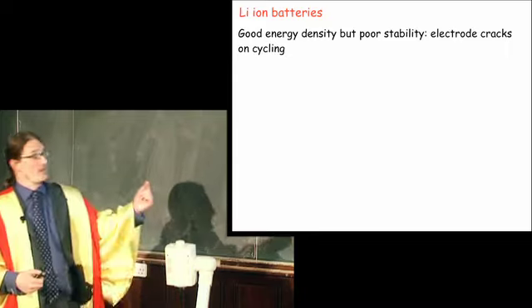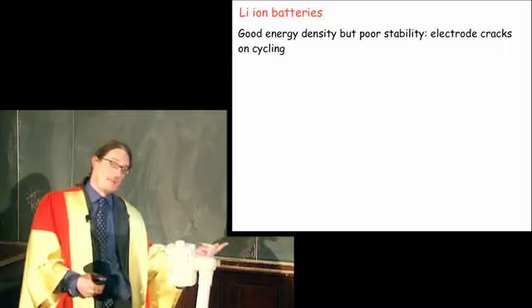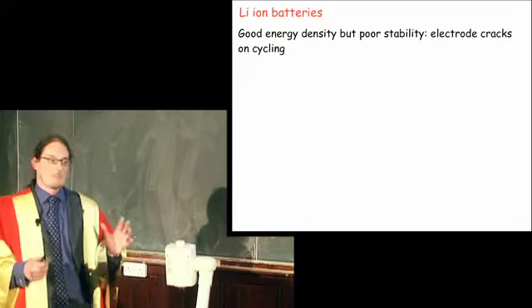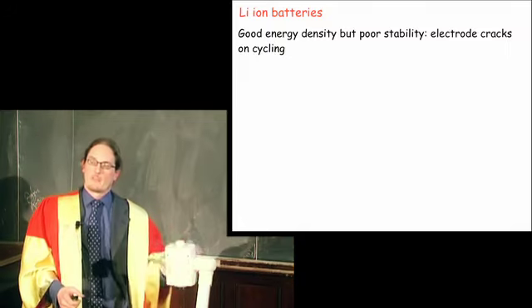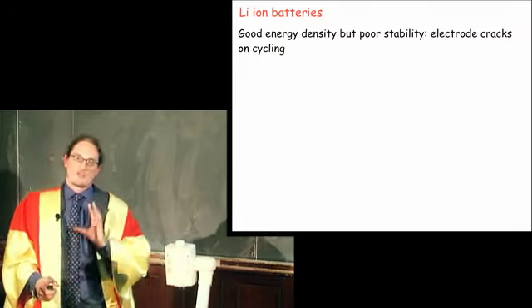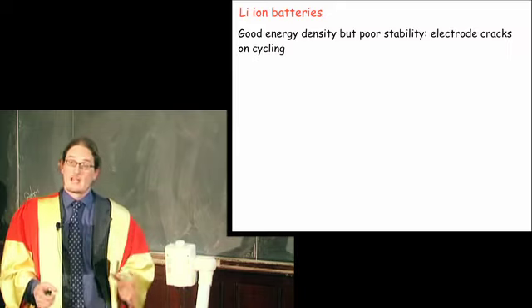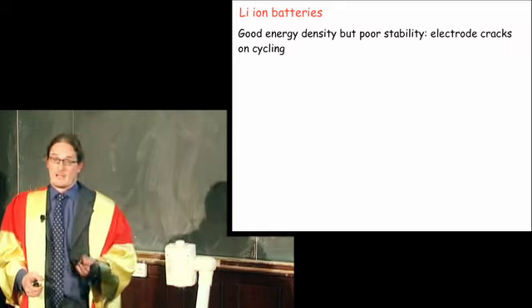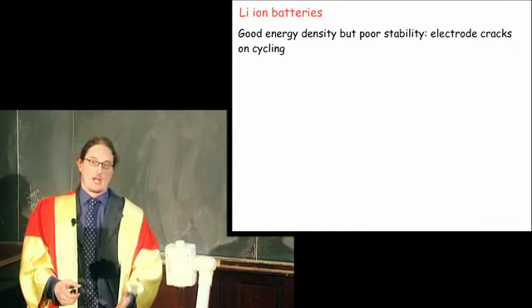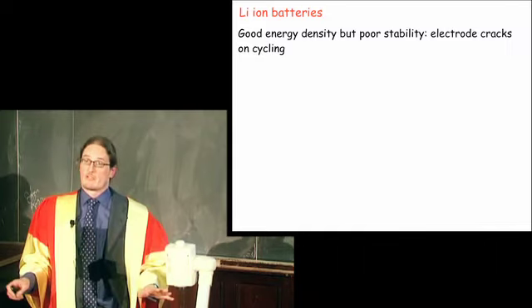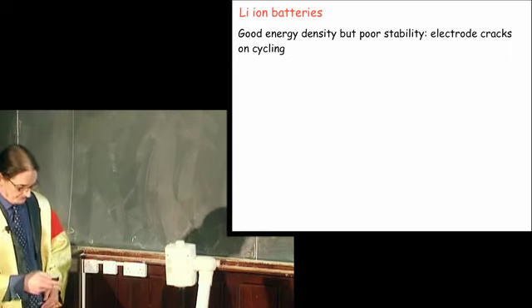You use it, the lithium ions come out. And then you charge it again, they go in, then they come out, in, out, many, many times. Now that process of putting the ions in and taking them out stresses the electrode material greatly and ultimately results in cracking. Small cracks mean that your battery life goes down a bit, big cracks means your battery dies. This has always been a problem.